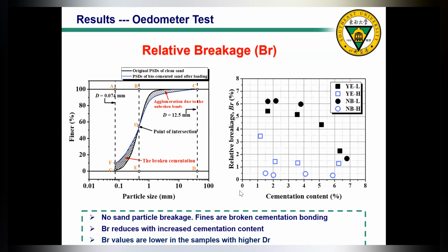Firstly, we also did a control test. For the clean sand, after compression, we didn't see any noticeable change in the particle size distribution curve. It means that the calcareous sand particle itself does not break. So we can see that the generated fine particles during the compression of biocemented sand are from the broken interparticle bonding.